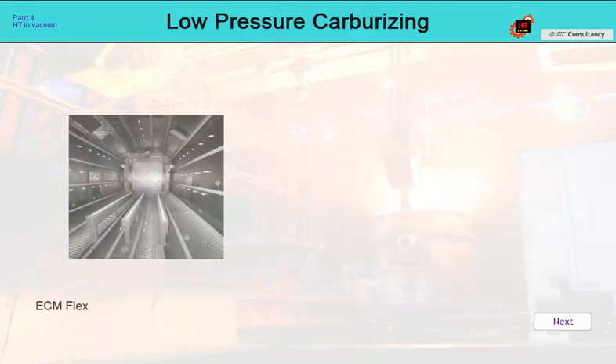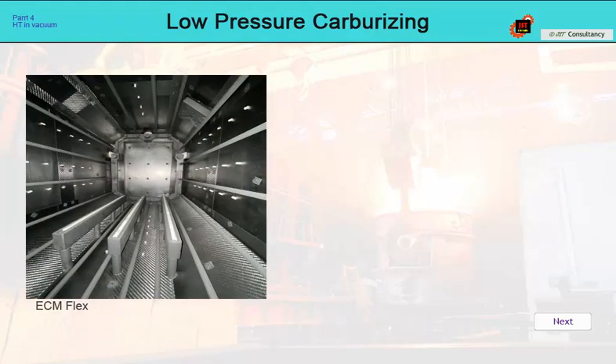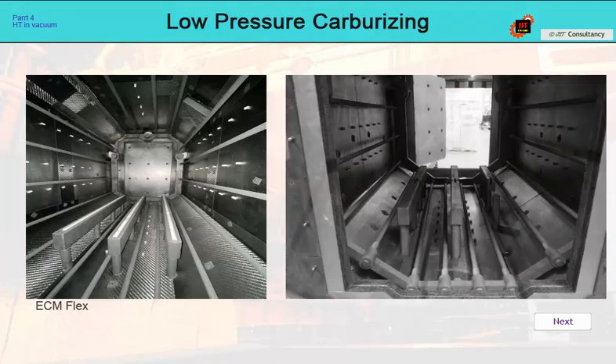In order for the carbon to be evenly distributed throughout the batch, an even distribution of acetylene in the heating chamber must be ensured. This is not entirely easy, because the total pressure of up to 10 millibar during carburizing is in the area close to laminar gas flow between the inlet and outlet to the pumping system. This may mean that gas may not reach some areas at all. To minimize this effect of gas distribution in the carburizing cell, it is necessary to properly design the inlet nozzle system. In ECM furnaces, there are more than 80 of them in the heating chamber.